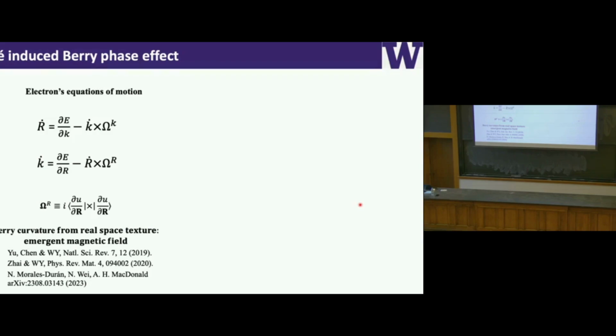This was pointed out by my collaborator Wang Yao at the Hong Kong University. So we know that we can look at the electrons' equations of motion in real space. Here, the first equation considers the position, and the second considers the crystal momentum. So if we look at the first equation, on the right, the second part is k-dot cross Omega_k. Here k is the crystal momentum, and Omega_k is the Berry curvature in momentum space. So this Berry curvature in momentum space, considered as a pseudo-magnetic field, will give rise to this valley Hall effect.